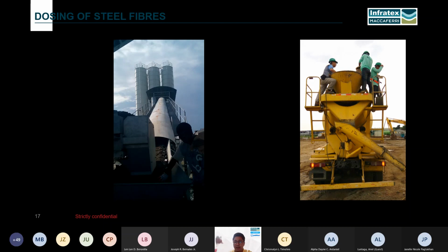However, if there are cases wherein the batching plant is too far from the site, say the mixing truck will take more than 1 hour of travel time, it's best to do the dosing at site at the back of the mixing truck. In dosing at the mixing truck, the drum speed must be at the highest speed. Then after completely dosing the steel fibers, make sure to continue mixing for at least 5 minutes or 1 minute per cubic meter of concrete. So if you have 10 cubic meters of concrete, continue mixing for 10 minutes.